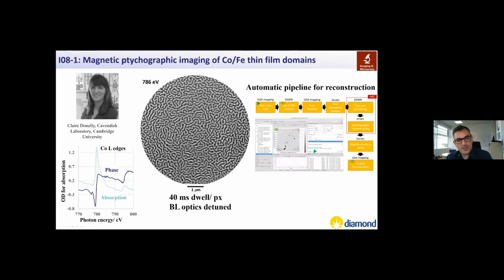In the soft X-ray regime, for quite some time we had a scanning transmission beamline, but recently we are also pushing a new branch line, which is dedicated to ptychography. It's called I08, so it's a second branch of an existing beamline. We see some early research done by Claire Donnelly and a group looking at ferromagnetic domains, in this case a test sample with cobalt iron. So this beamline just came online very recently.